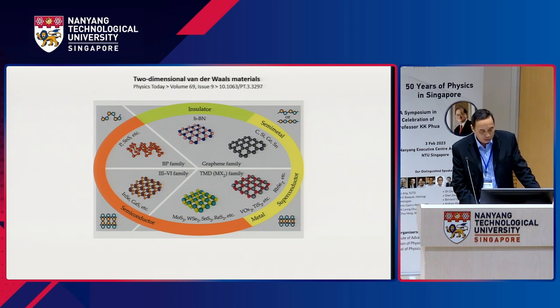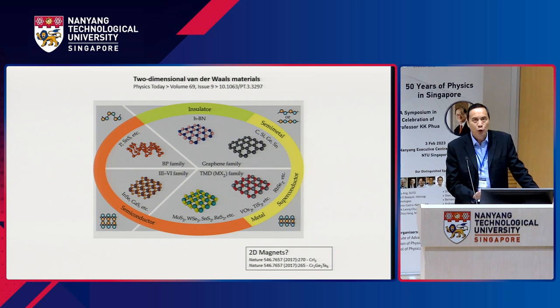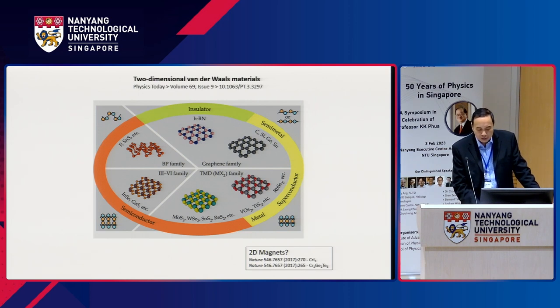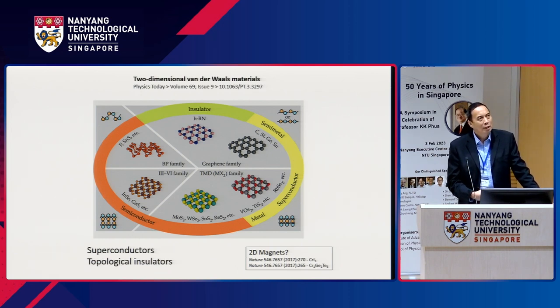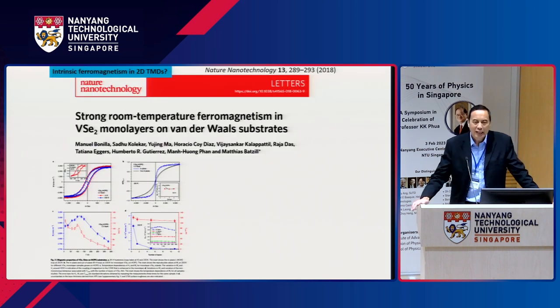So we also looked at other 2D materials. We started off with TMDs, and we found it interesting because it was stated that 2D materials could not be magnets. And so there's this question mark. Until 5 years ago or so, people had not discovered magnets in 2D materials. The reason is the Mermin-Wagner theorem, which says you have to introduce some asymmetry in the system in order for it to be magnetic. And hence, the first magnetic system we studied was because we saw this Nature Nanotechnology paper published by a Florida group that showed fairly large magnetism in vanadium diselenide.